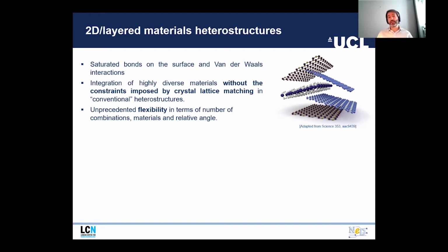Because these materials have saturated bonds on the surface and typically are held together by van der Waals interaction, we can combine them in any sort of order and also angle, without the constraint that we normally have in three-dimensional materials. This property results in a really incredible flexibility. First of all, because the family of two-dimensional materials is very large, we have a lot of materials to choose from, and we can combine them in whichever order and whichever angle.